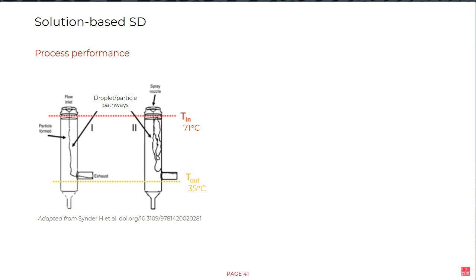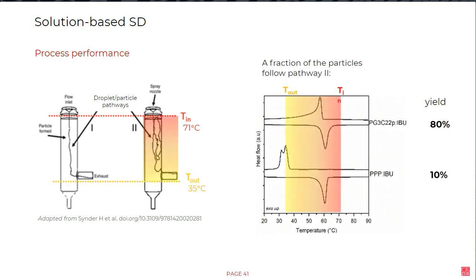On the other side, not all the particles, unfortunately, follow this ideal pathway. They can also follow pathway number 2, in which after the particle is formed, it can be entrapped in a recirculating eddy, which eventually will bring the particle to the inlet without having the evaporative cooling effect during solvent evaporation, so it will actually get exposed to 71 degrees. What happens with these particles? What happens when they are exposed to such high temperature?